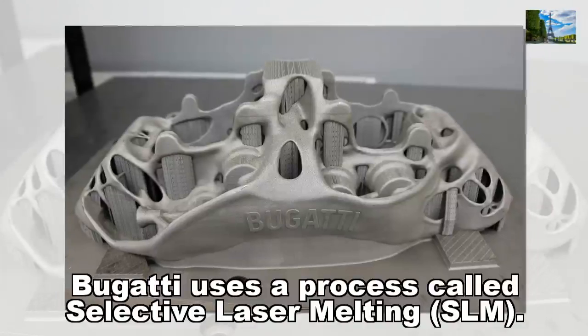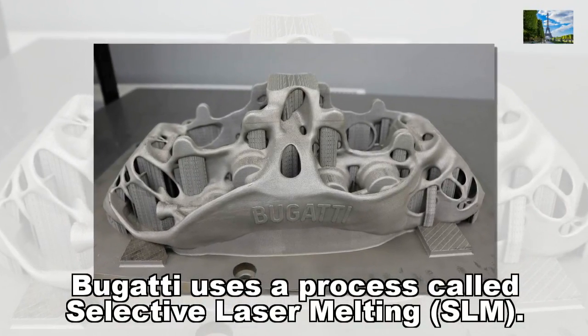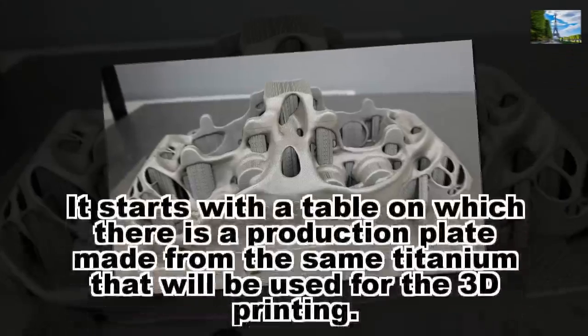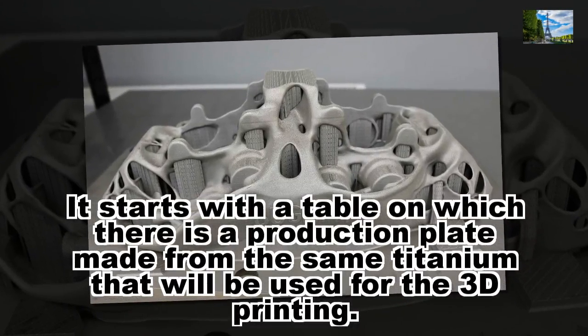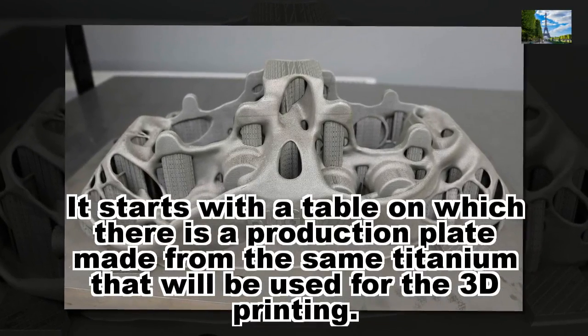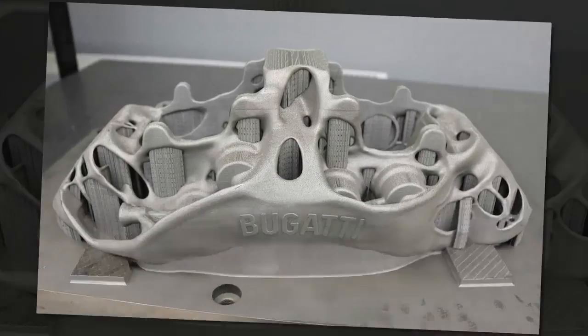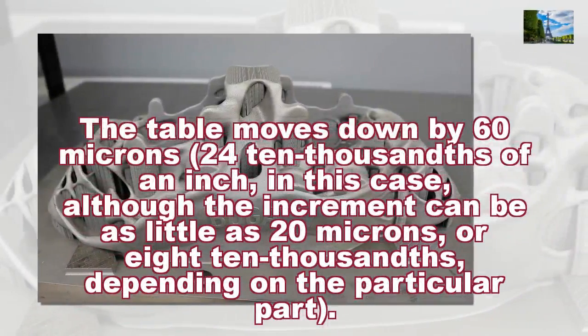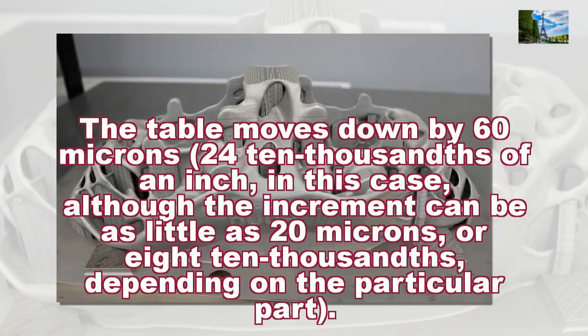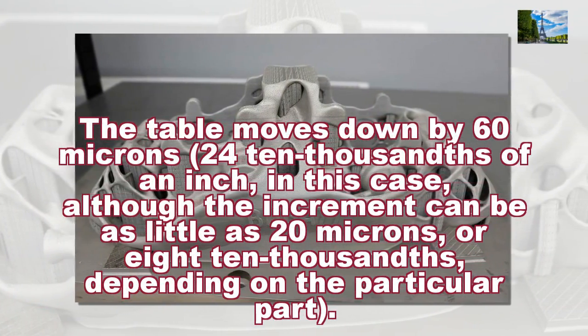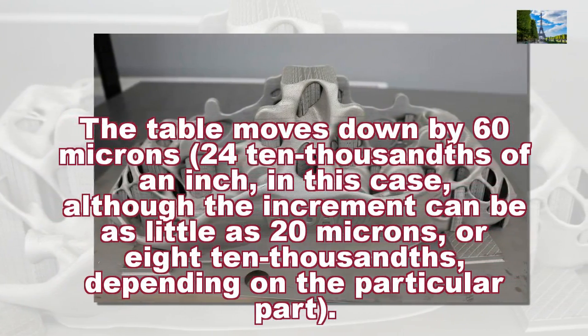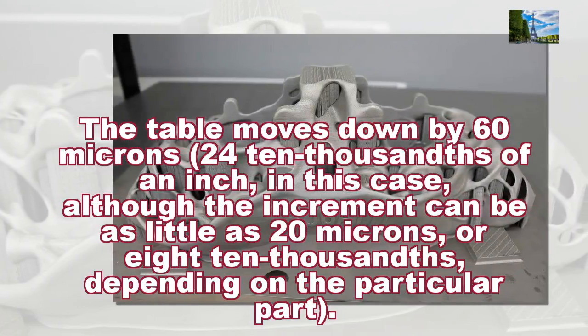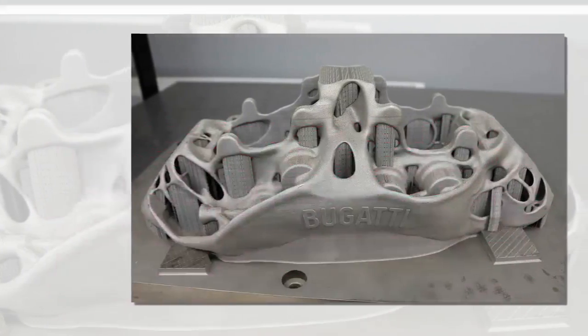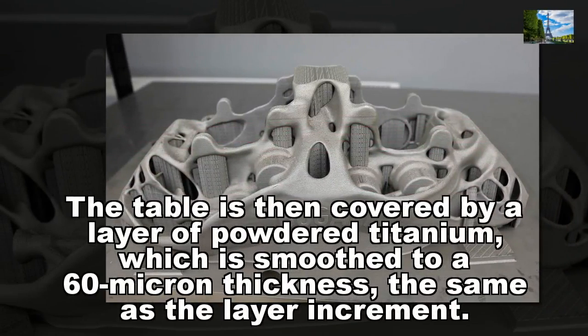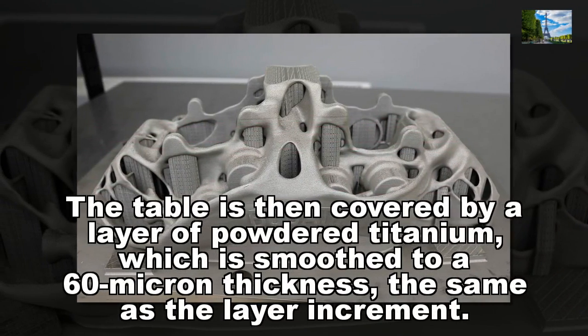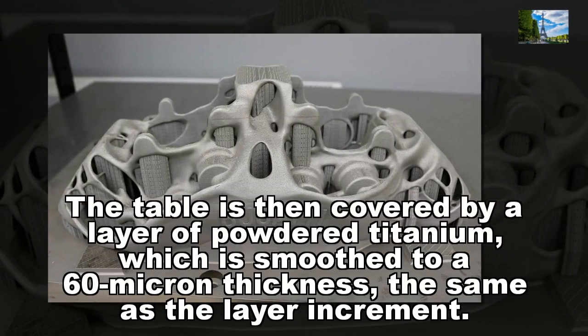Bugatti uses a process called selective laser melting, SLM. It starts with a table on which there is a production plate made from the same titanium that will be used for the 3D printing. The table moves down by 60 microns, 24/10,000ths of an inch, in this case, although the increment can be as little as 20 microns, or 8/10,000ths, depending on the particular part. The table is then covered by a layer of powdered titanium, which is smoothed to a 60 micron thickness, the same as the layer increment.